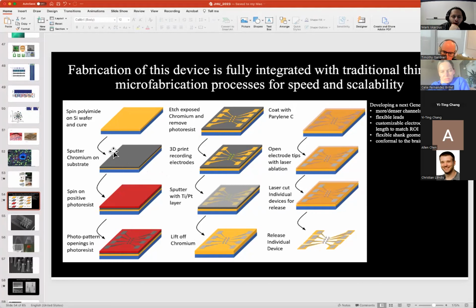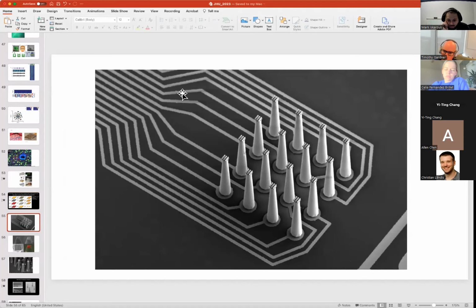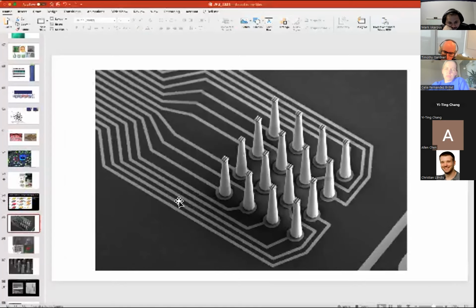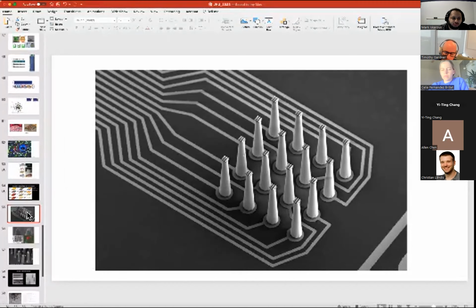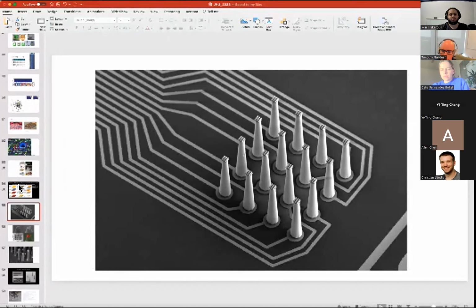Initially, this was a chromium mask for an important step in the process. And to make a long story short, we were able to fabricate these electrodes in standard cleanroom lithography steps for polyimide, and then 3D printing, and then metallization of everything after that 3D print process, followed by further liftoff steps that would remove metallization from areas other than the desired targets. And a final step in this, yeah, go ahead.